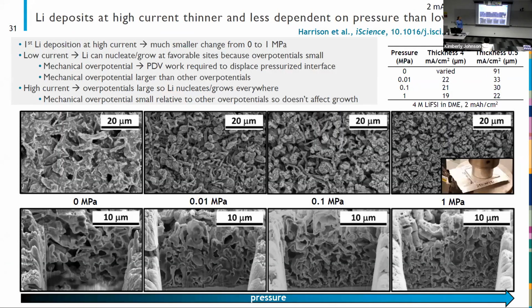So first I want to show you the morphology of the lithium metal that we plated at these various pressures. I'm not showing you 10 megapascals because we could not plate lithium at this current density at that pressure. And we think, again, that's because we shut down transport. It's already limited at the high current density. We add the pressure component and we can no longer do electrochemistry.